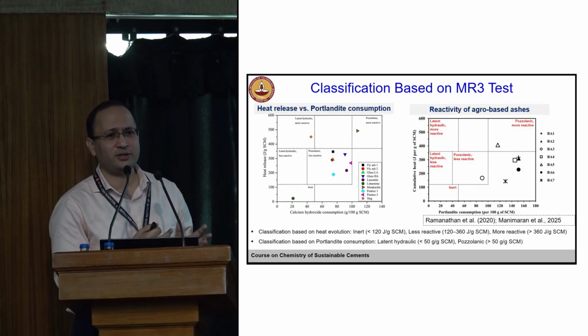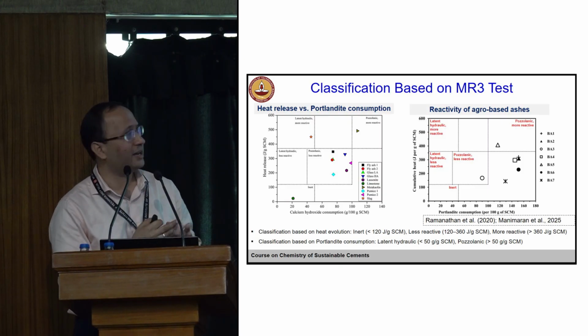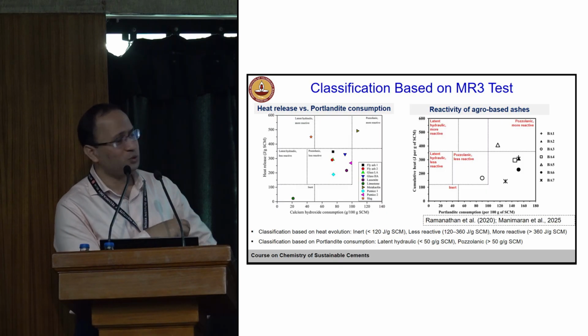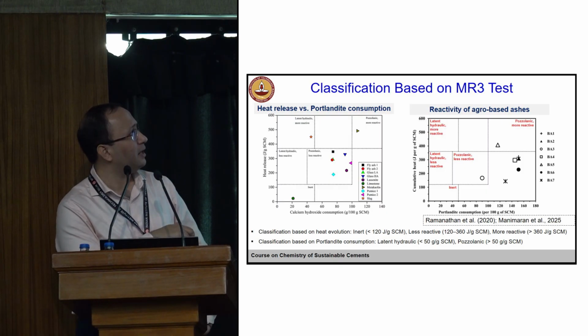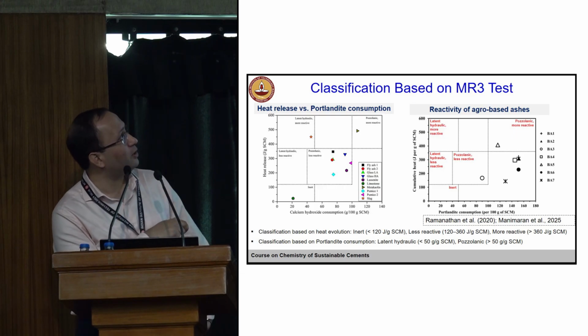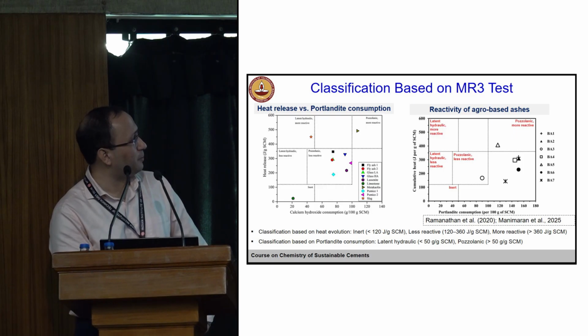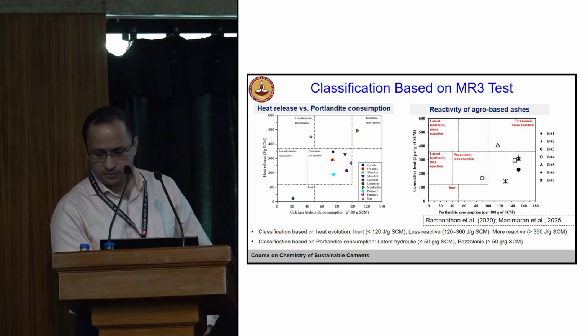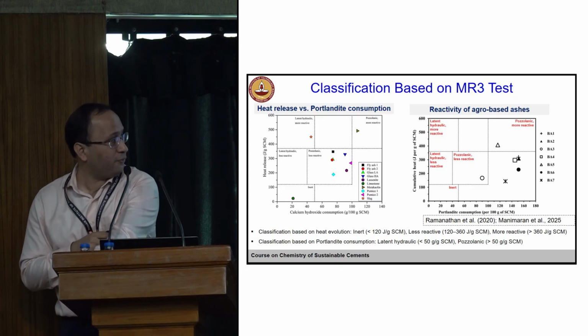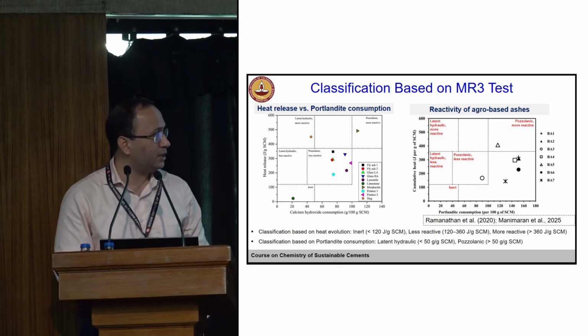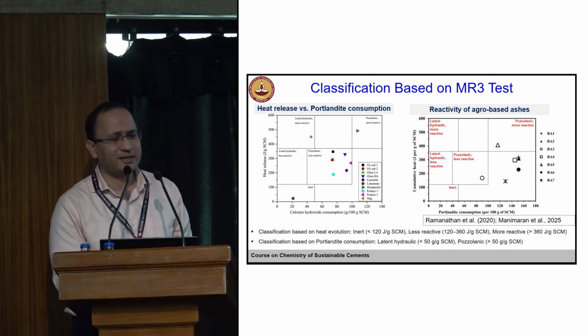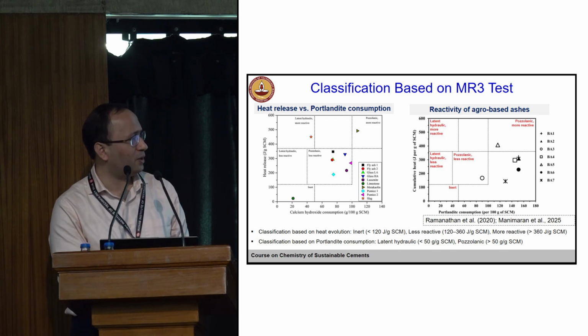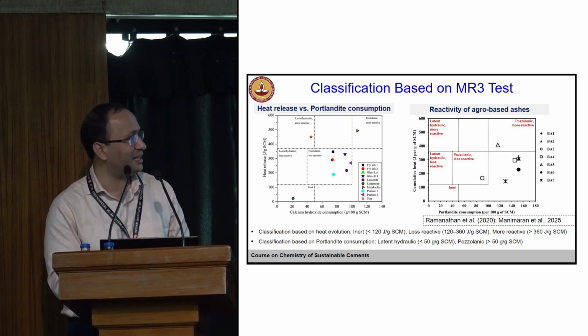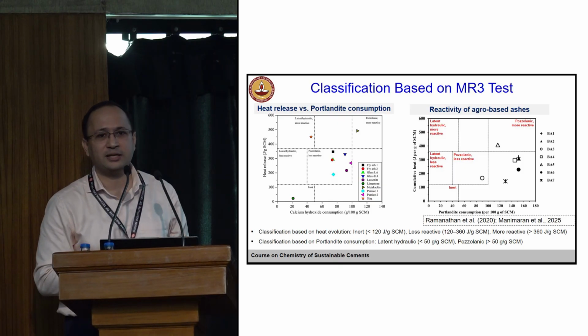These boundaries are not well defined. Again, this was proposed in this study, but you see kind of a scatter, right? You can see there are some latent hydraulic systems, but more reactive, right? Typically, if the heat of hydration is less than 120 joule per gram of SCM, then it's considered inert. More than that, let's say 120 to 360, it's less reactive, more than 360 joule per gram of SCM, and all this can be easily done using isothermal calorimetry.